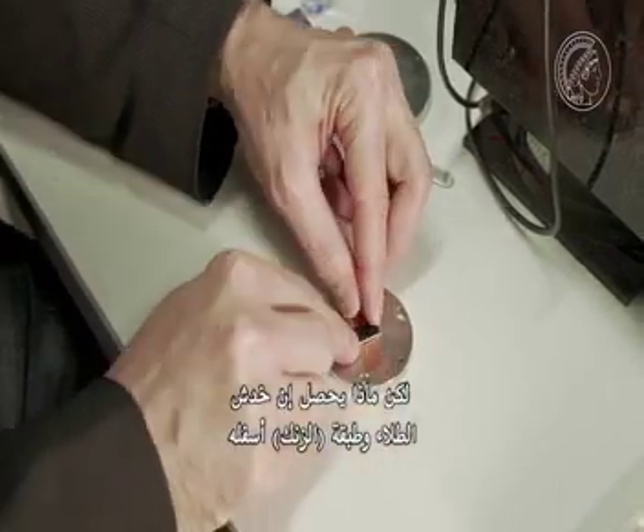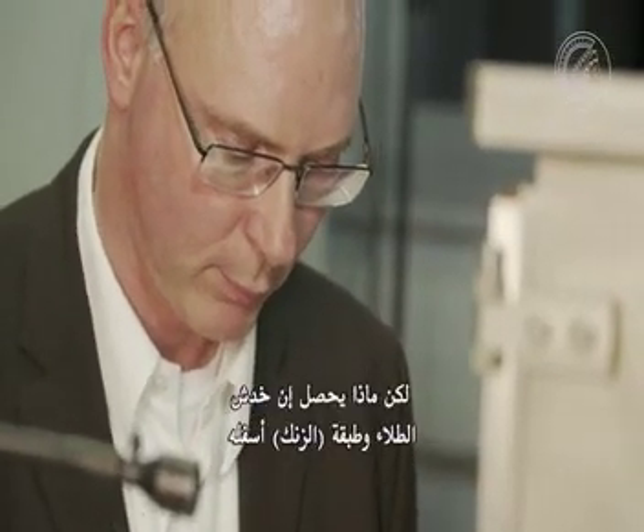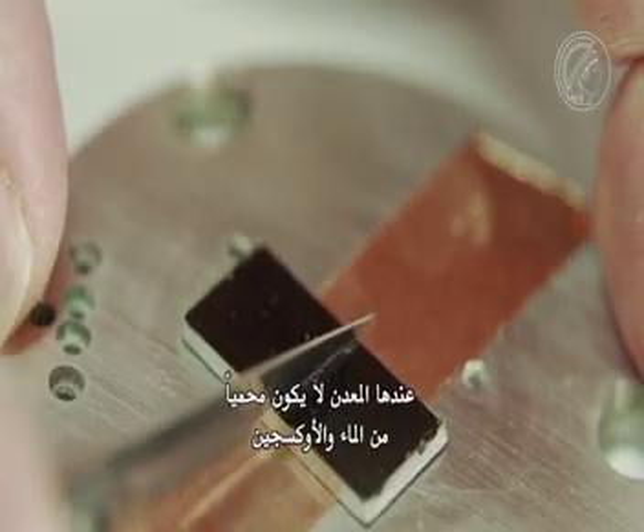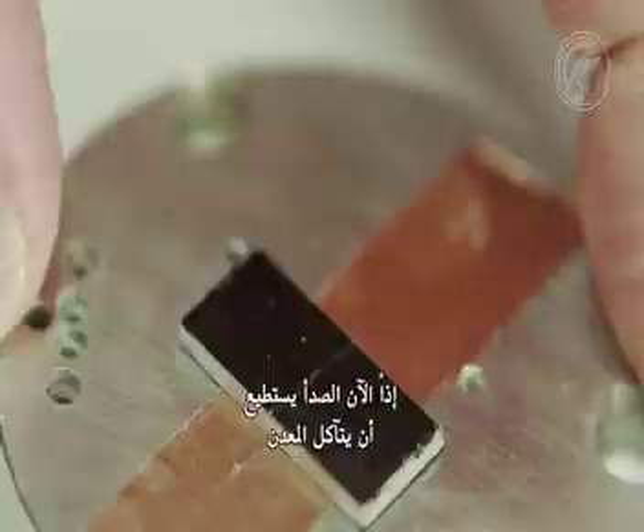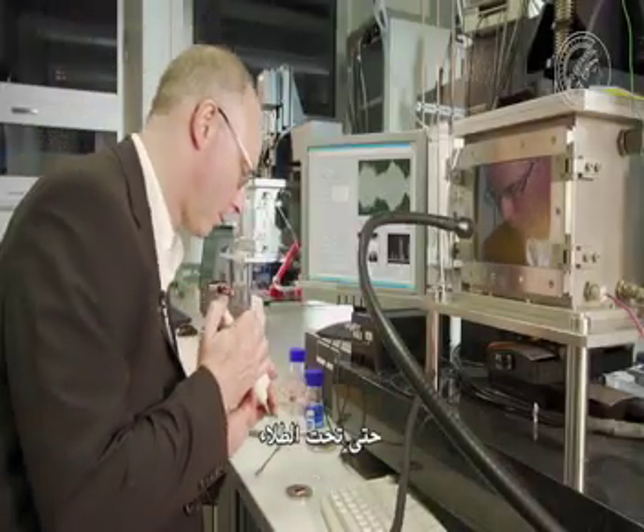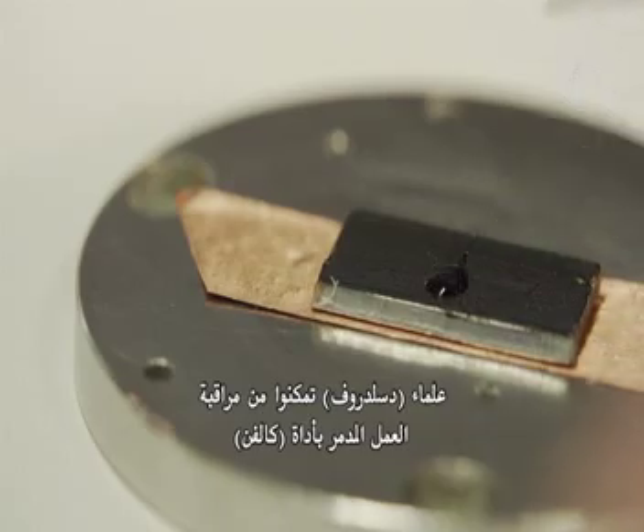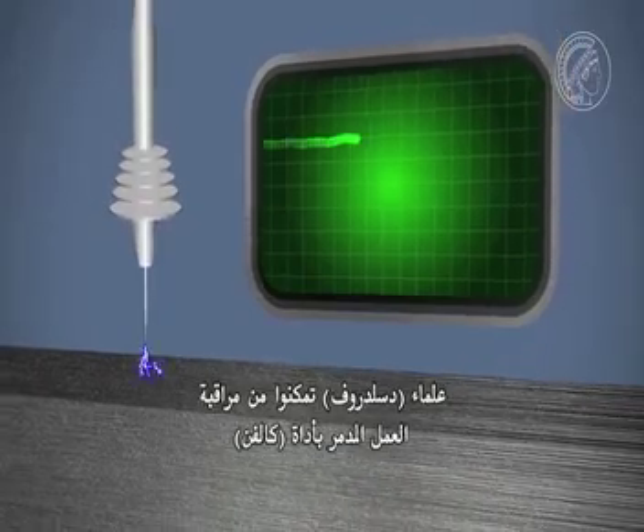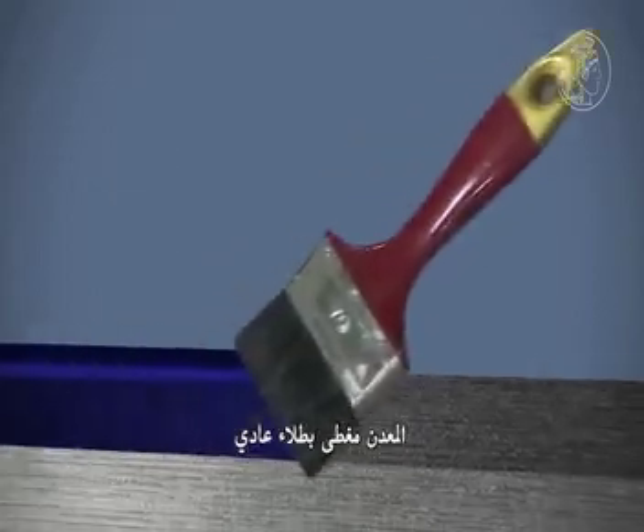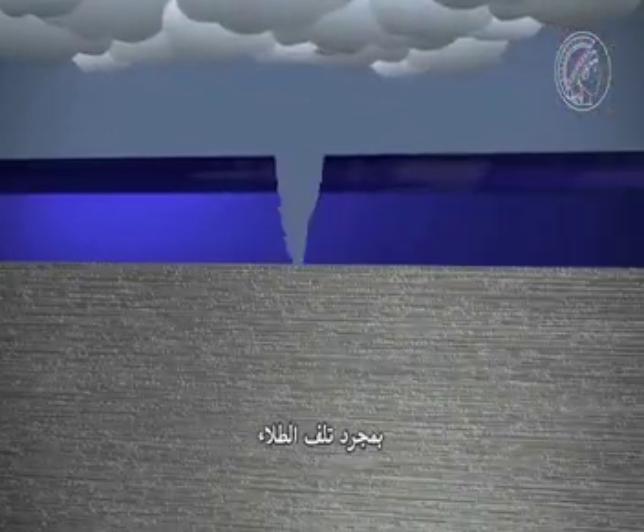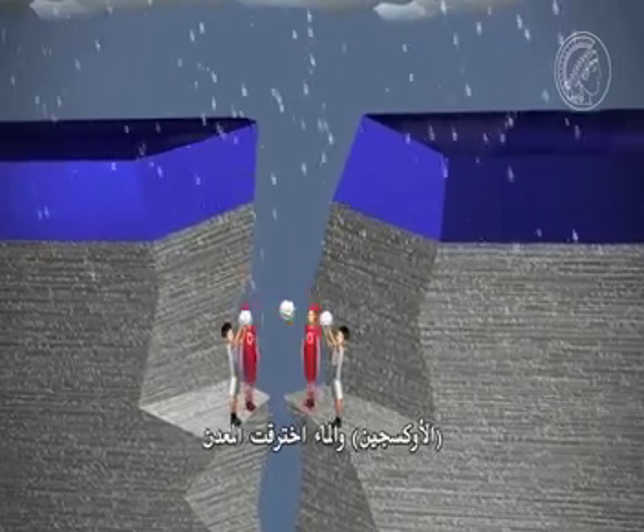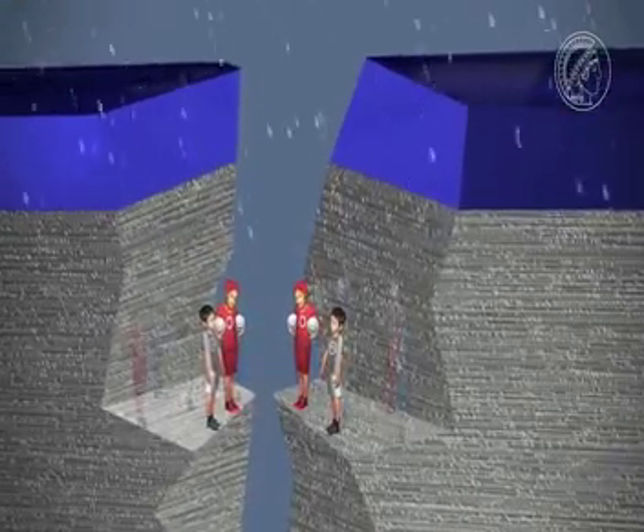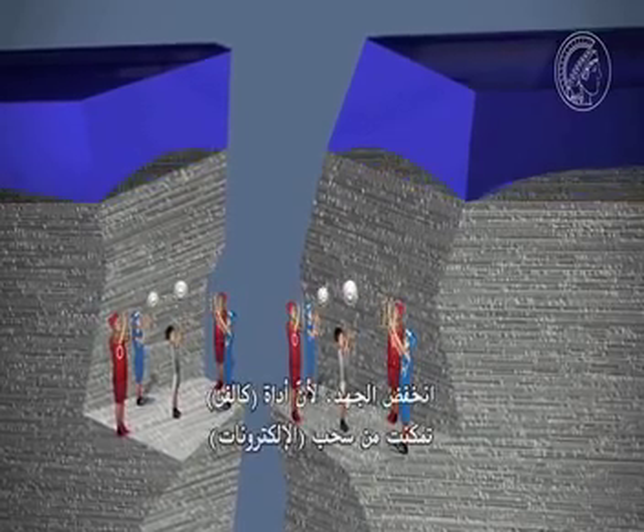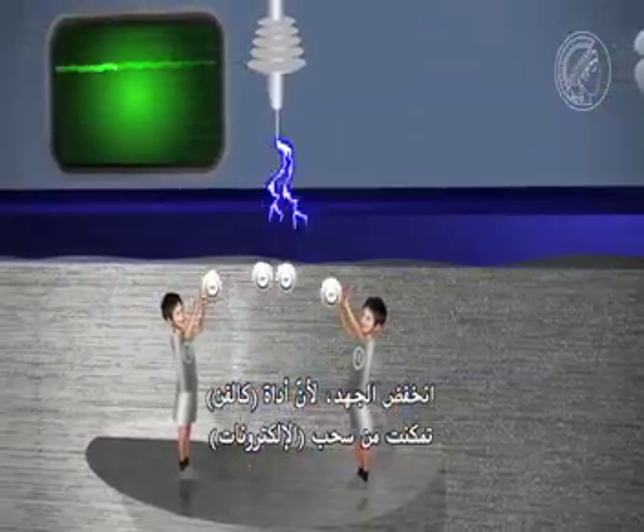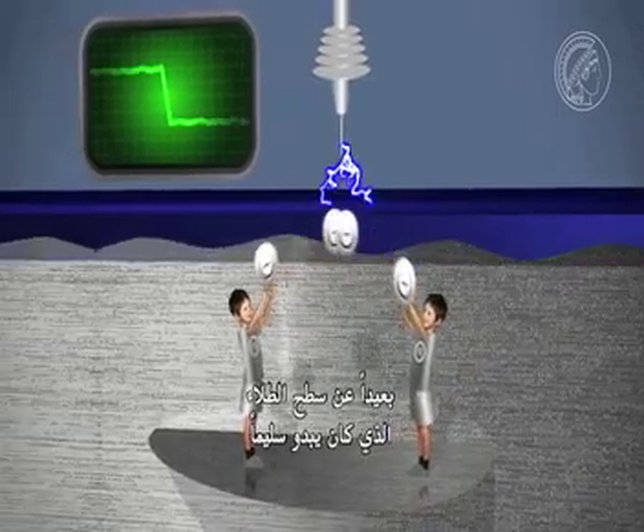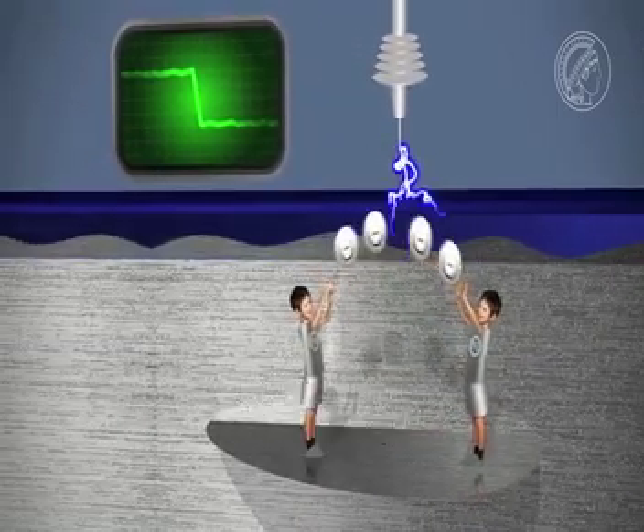But what happens when the layer of varnish and even the zinc beneath it get a deep scratch? Then the steel is no longer protected from water and oxygen. So now the corrosion can eat into the metal, even underneath the varnish. The Düsseldorf scientists were able to observe the destructive work with the Kelvin probe. The metal is coated with ordinary varnish. As soon as the varnish is damaged, oxygen and water penetrate through to the metal and corrosion begins. The varnish peels off the metal. The tension sinks because the Kelvin probe can more easily draw the electrons away from the surface of this varnish, which only appears to still be intact.